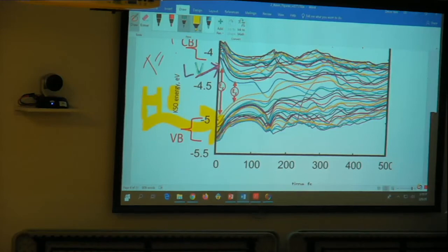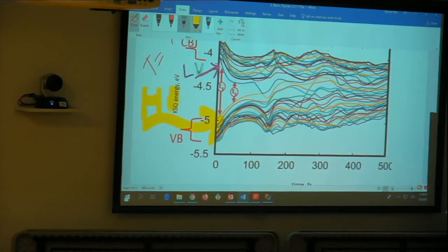You just need to realize it and see that it is one of the major mechanisms that may undermine trustability of the results. Possibly there are ways to mitigate it, but you need to realize it and see how strongly it affects. So the temperature fluctuation changes the gap from 1 eV to 0 eV. Basically, it makes it a semiconductor to metal transition.